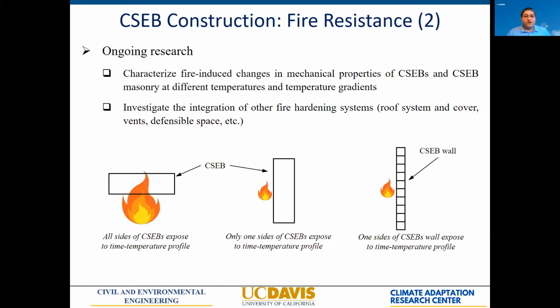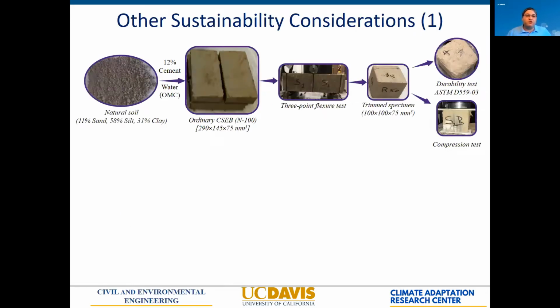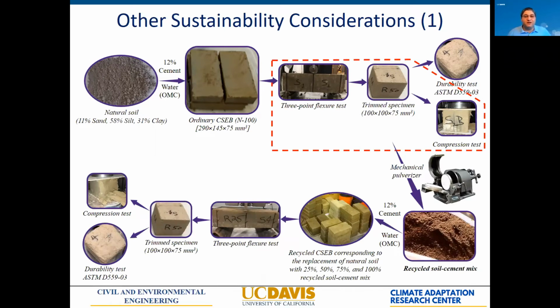But we are doing all of these different tests, and we are also investigating how to integrate the other fire hardening systems like roofs, covers, vents, and defensible space, so that you really obtain a house that is fire resistant. We are also investigating other sustainability considerations. For example, we have done an investigation on recycling the material used for CSEBs. I'm not going again too much into the details, but what we found is that we can reuse the material from damaged bricks to build new bricks that are as good, if not even better than the original bricks. So the material is fully recyclable, which is obviously very important in terms of sustainability.